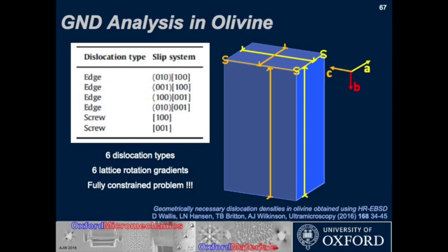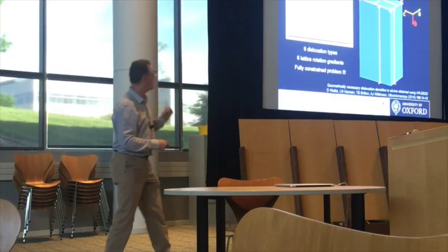And so the dislocation types, because this cell has a very long B axis, I tend not to have dislocations with a Burgers vector along the B, because they're just big. B squared, GB squared, then becomes too big. They're an unfavored dislocation system. So instead I get the dislocation systems that I've got in here.